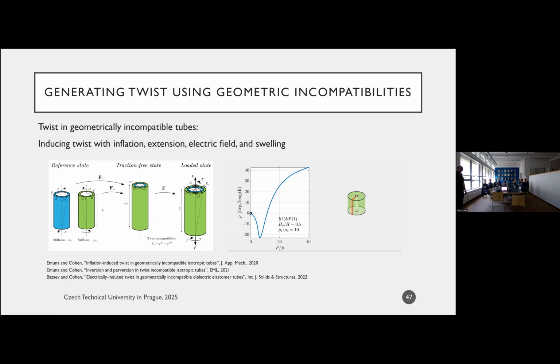So what you see here is a tube, and we're going to inflate it. This is a bilayer tube. We constructed it in this method, and we're going to inflate it, and I want to show you what it does. Okay, so when we start inflating it, you can see first it twists clockwise, right? At a certain point, I keep inflating it, and then it reverses the direction of twist. Now we twist in the other direction, right? This is very strange. And if I keep inflating it, all of a sudden, it also rotates completely, and now it turns into a different direction from the beginning. Now it rotates clockwise, right?